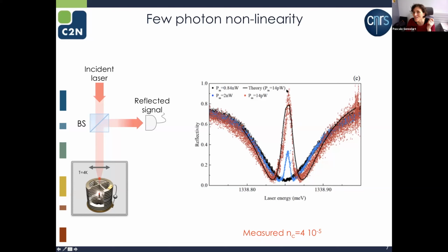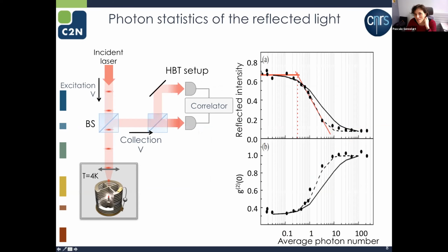What shows that it's a single atom mirror is that when I increase the power, very, very little power, on the order of picowatts, I saturate the transition. This peak disappears and I end up as if the cavity was empty. When I saturate the transition, it's as if there is no quantum dot in it anymore. So we can show that it's actually a device with a single photon non-linearity by now sending light pulses. I want to send light pulses because in a pulse, I can tell how many photons I have on average. And I can now plot the reflectivity of the light as a function of the average photon number.